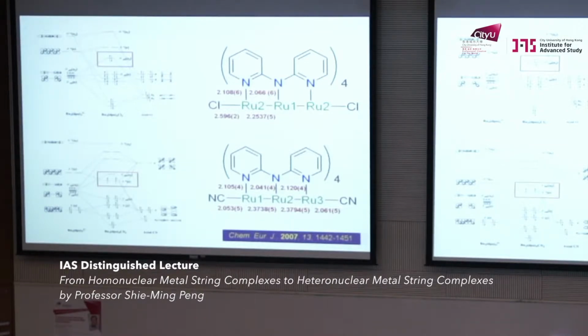Okay, so simple molecular orbital theory says this is a pi-based ligand. The pi orbital will be lower, and it will interact with this one and the even higher orbital. But this pi-acceptor ligand has an empty pi star orbital, which will interact with the pi star orbital, lowering the pi star orbital below the sigma nonbonding, and you will populate 2 electrons on this pi star orbital, making the bond order go from 3 to 2. That explains the bond lengthening to 2.37.